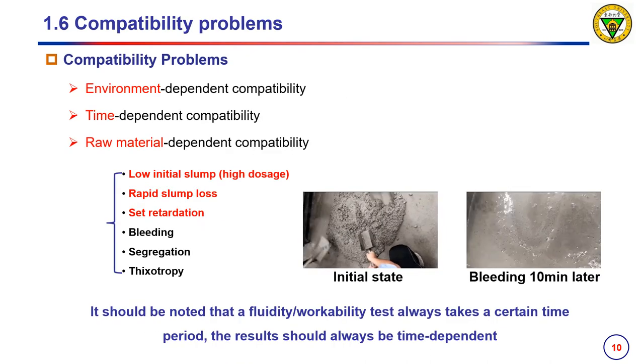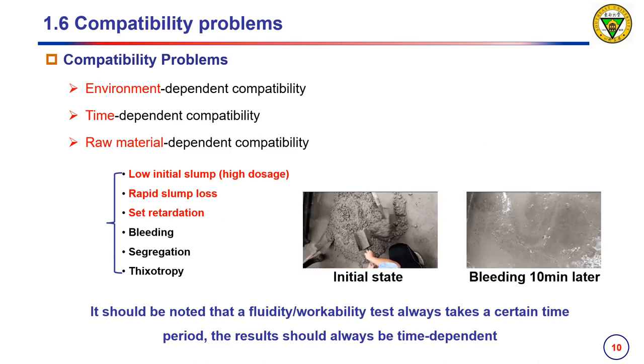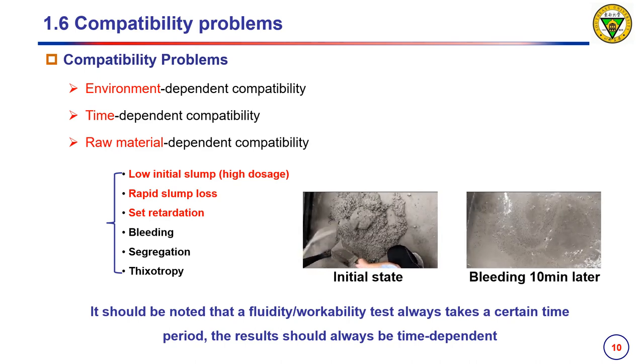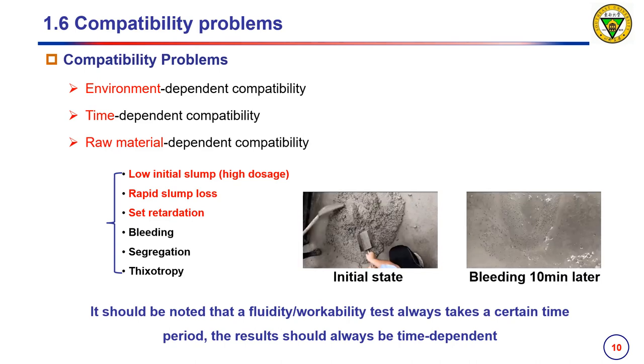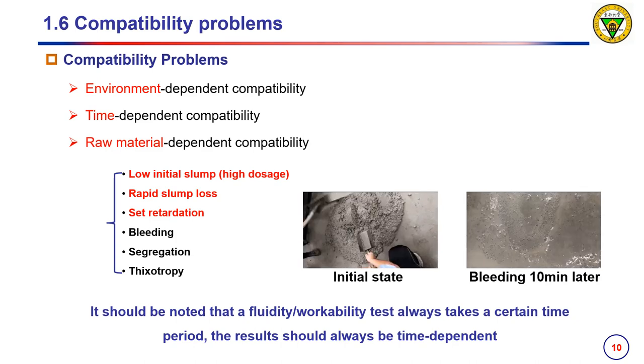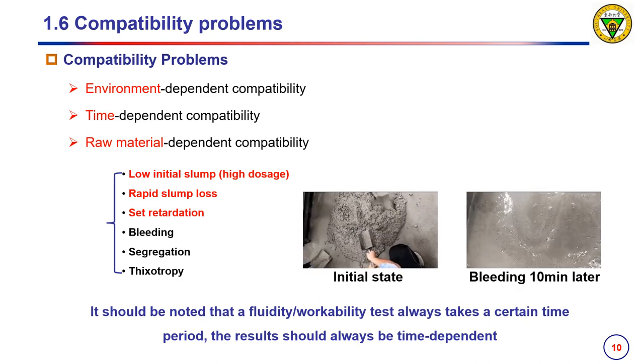In application, compatibility problems always occur, associated with the environment, time development, and the property of raw materials. Inappropriate application might induce low initial slump, rapid slump loss, and set retardation. It should be noted that the flowability test always takes a certain time period, so the result should always be time-dependent.